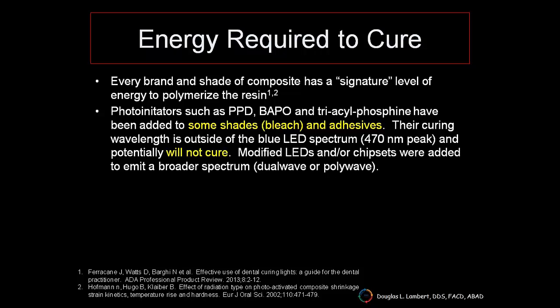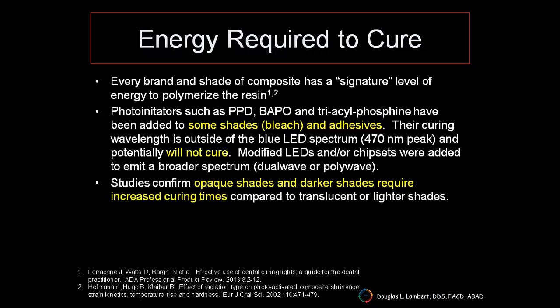Their curing wavelength is outside of the blue spectrum, which has a 470 nanometer peak. So usually somewhere between 420 and 490 is the blue spectrum. And potentially these will not cure because they aren't in that spectrum of wavelength. So the LEDs had to be modified with chipsets that electronically changed the spectrum and allowed them to emit a broader spectrum. And that's where the dual wave or the poly wave lights came from.